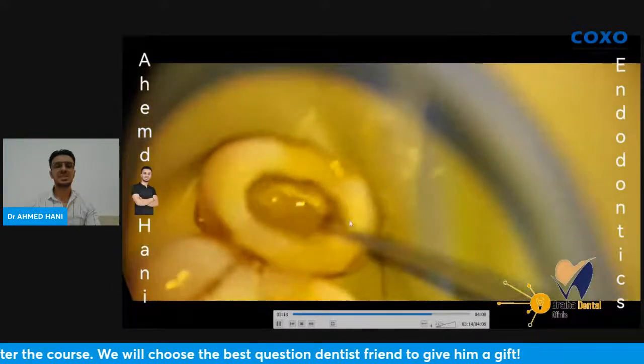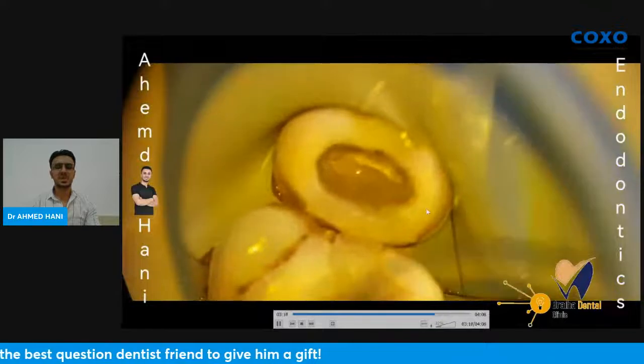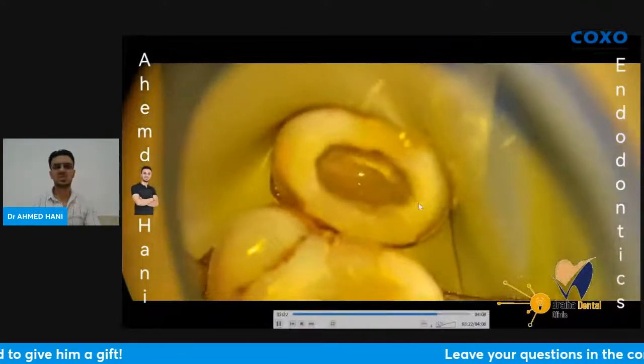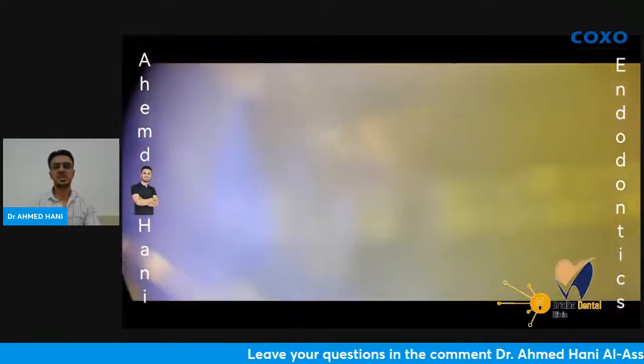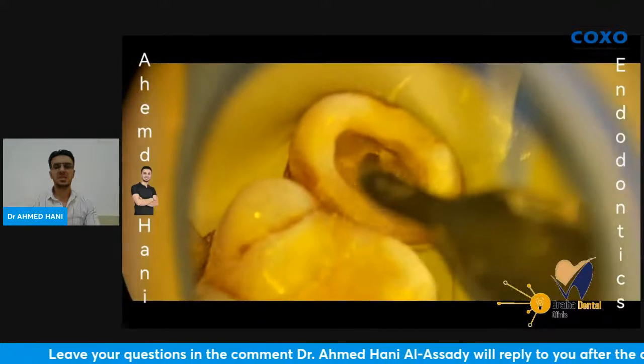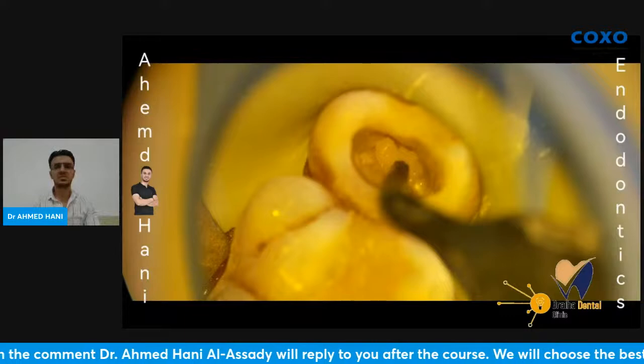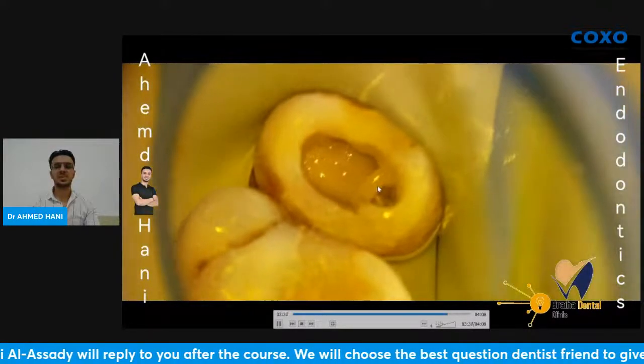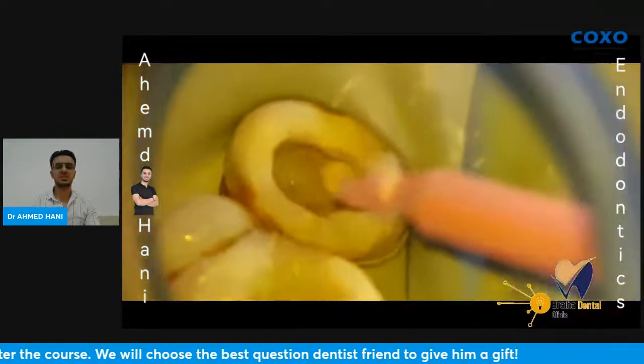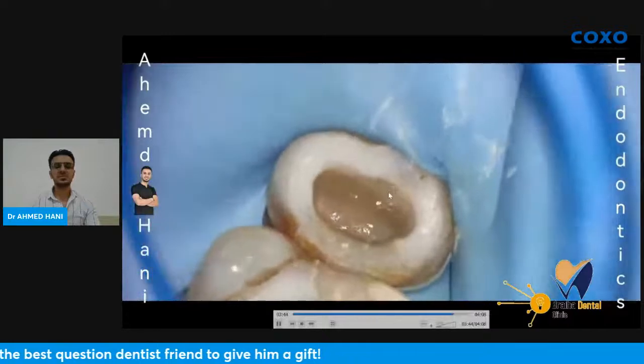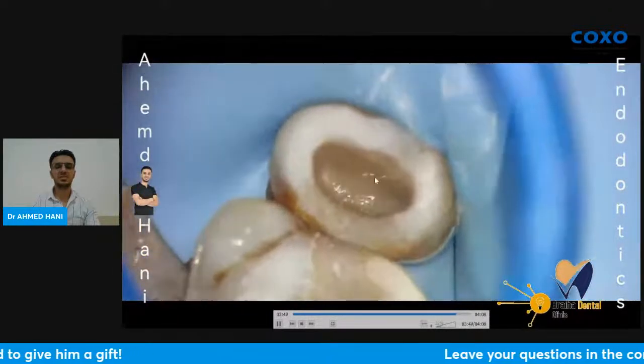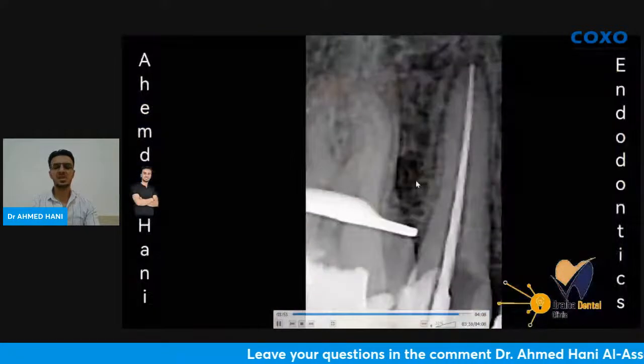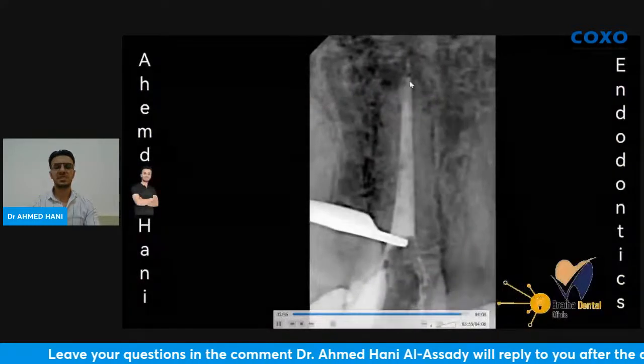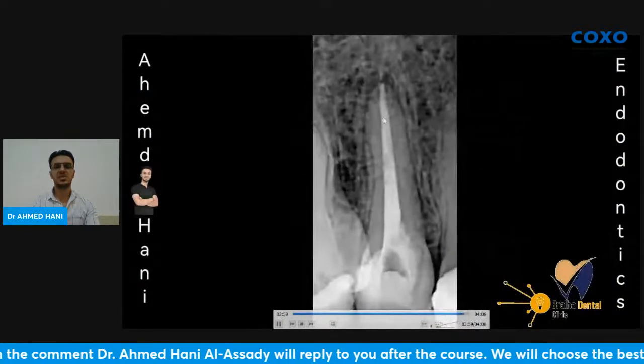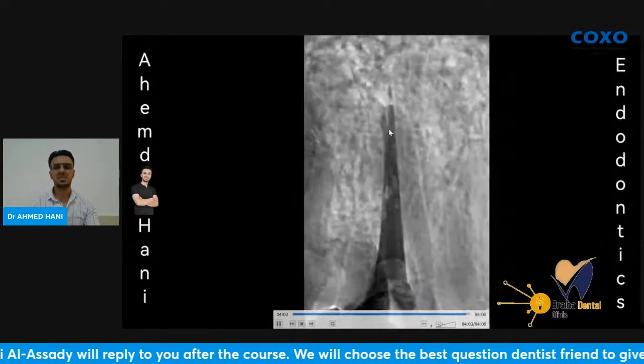This type of obturation also strengthens the tooth, as it acts as a monoblock within the root. It is bonded chemically and bonded to the dentinal wall. In such cases, we should change the final irrigation protocol to get all the benefit of this material, to get it bonded to the dentin. So this is the final after putting a fiber reinforced composite. Let's see the X-ray. This is a perfect apical seal. Also there is a split filled with bioceramic putty, perfect apical seal. This is a split filled by bioceramic putty, which was missing preoperatively.